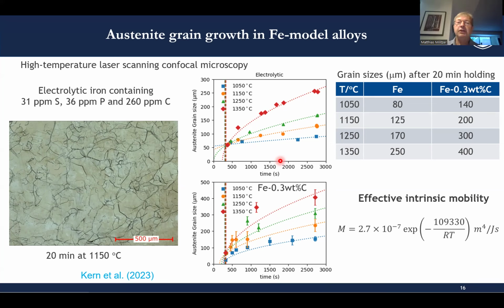Then they also did grain growth studies in iron carbon alloys, here with 0.3 weight% carbon added. And what they found out is that adding carbon increases the grain growth rates, maybe by a factor of 2. So after 20 minutes of holding, the grain sizes are summarized here. We have to keep in mind the scale here is from 0 to 300 micrometer, here from 0 to 500 micrometer. So we reanalyzed these data and basically used the data for the iron carbon system to extract an